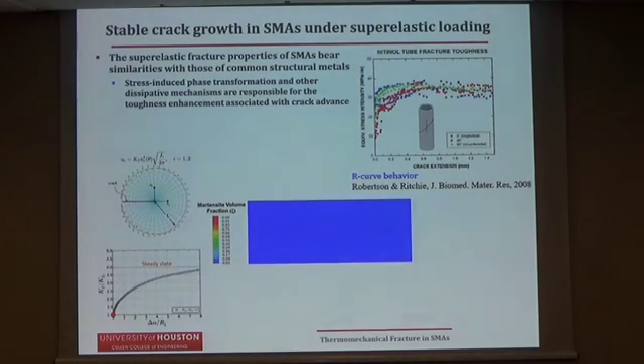However, the fracture of shape memory alloys under pure mechanical loading under isothermal conditions bears similarity to the fracture response of conventional elastic-plastic structural materials, in the sense that once the crack starts growing, it doesn't run unstably. Rather, there is a stable crack growth regime. As the crack propagates, material elements in front of the crack tip transform, or there is twinning or some other dissipative process. And this dissipative process, of course, dissipates energy that must be supplied by the external loading to maintain crack growth.